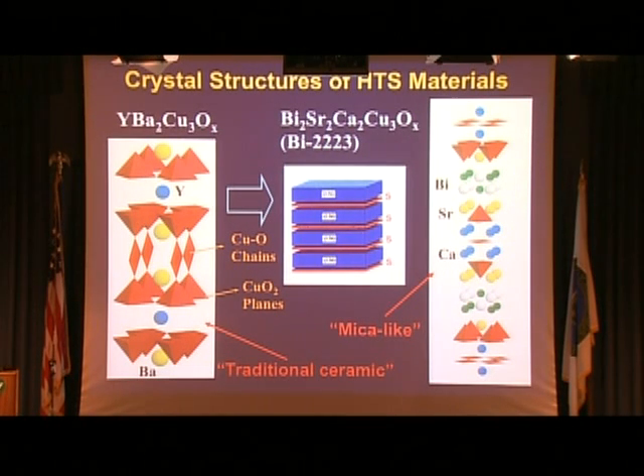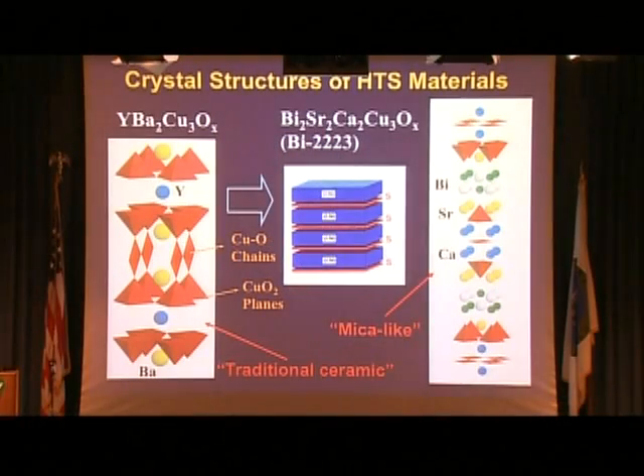So if you were to look at the crystal structure of two cuprate-based superconductors, one the YBCO, the other a bismuth-2223-based superconductor shown on the right-hand side, this entire family of cuprate-based superconductors can be viewed as consisting of two-dimensional red planes, copper oxide planes, which are the superconducting components, separated by non-superconducting insulating or normal regions. And as you increase the distance between these red planes, the transition temperature goes up. But the material becomes more two-dimensional because these planes are not as close to each other. So mechanically, the material structurally behaves more mica-like, and the YBCO superconductor has additional structural components, which are these copper oxide chains. It makes it much like a traditional ceramic material, mechanically, as well as it is more three-dimensional. So intrinsically speaking, its superconducting properties actually are far superior to all the higher TC materials in the same family.